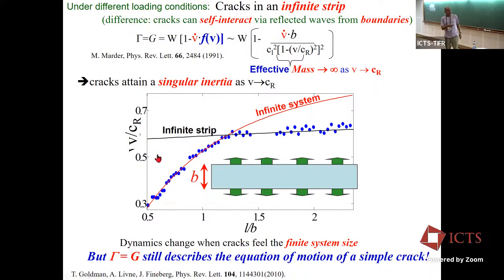So this is our infinite system, and B is the width, or the vertical size, of the system. When the crack gets to this scale B, where information starts to bounce back and interact from the boundaries, it changes its motion, and this straight line is exactly this prediction, again with no free parameters. So we have two equations of motion that work under different circumstances. Both of them assume they're driven by energy balance: the energy flowing into the tip of the crack is equal to the fracture energy, just different implementations of the same principle.